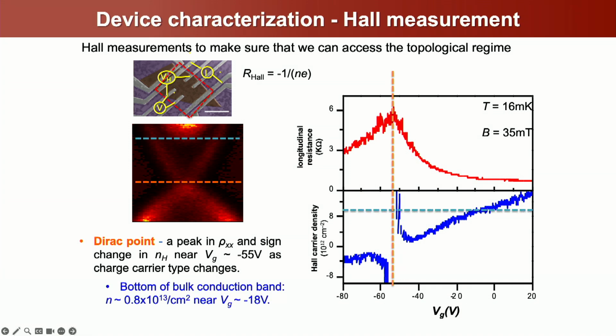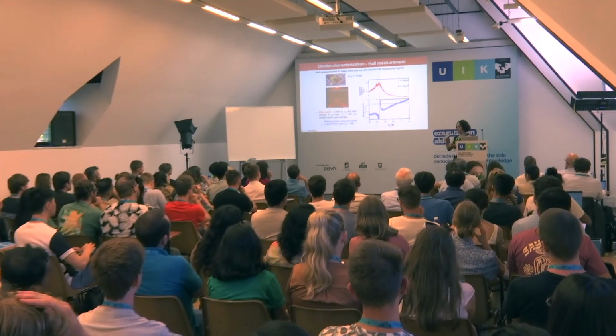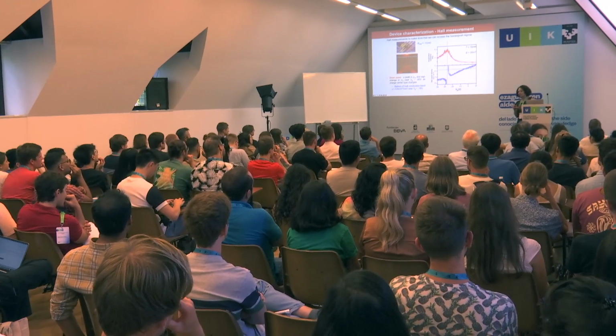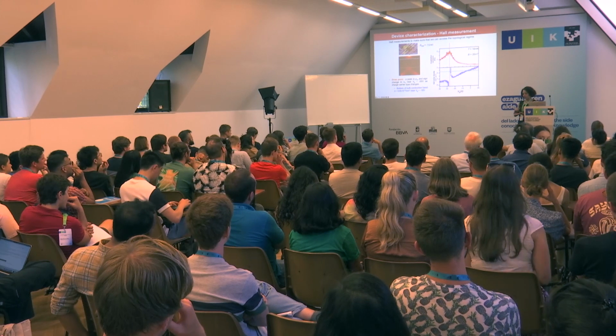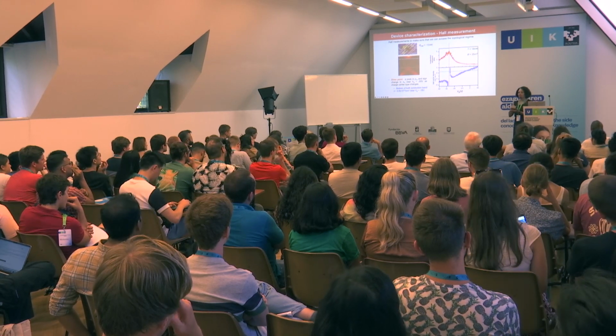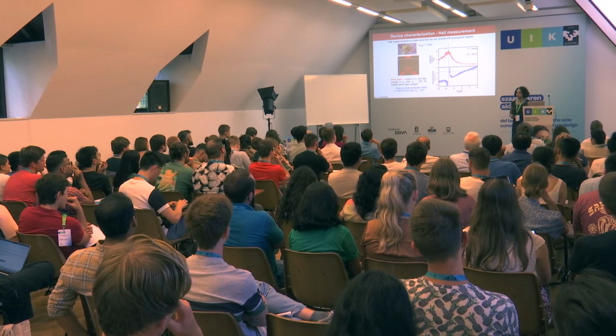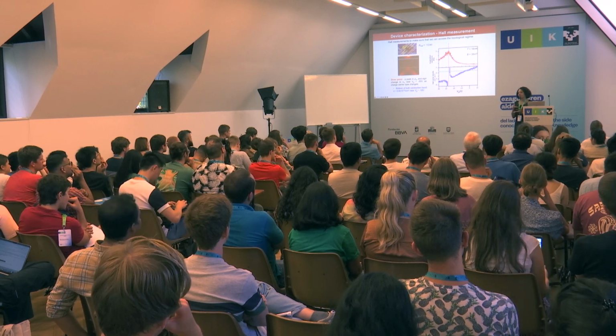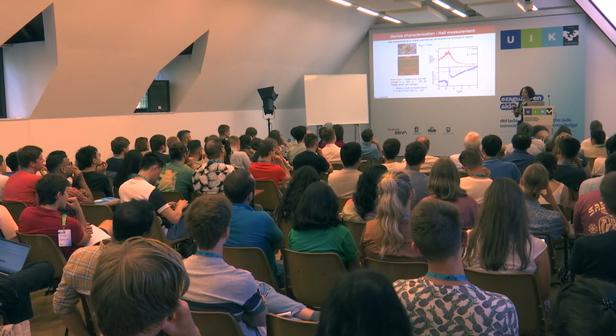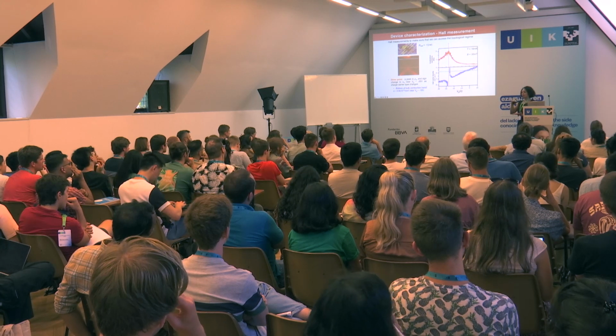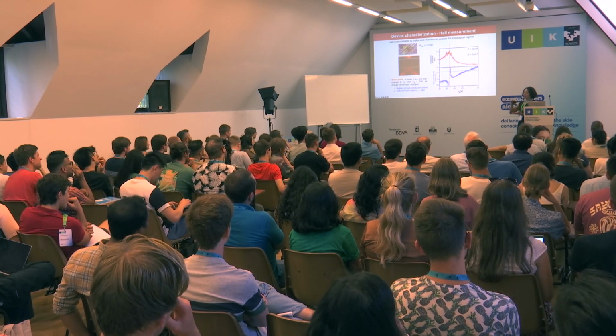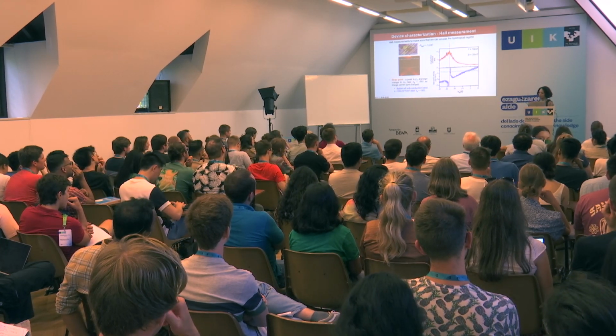Are you not worried about gating the two surfaces of the TI differently? Yeah, that's right. So we try to use very thin ones. We found that if they're less than about 20 nanometers, you can evenly gate the top and the bottom. This is a study that was done by a Maryland group a while ago, showing that if it's thinner than about 20 nanometers, you can basically gate them both together. As it gets thicker, you have to use both a top and a bottom gate, which avoids that. But in our case, it's thin enough.